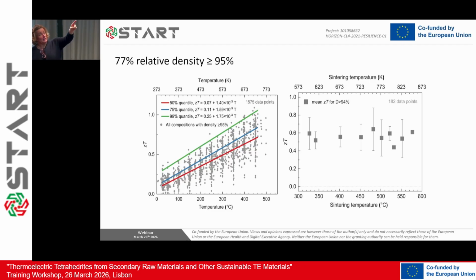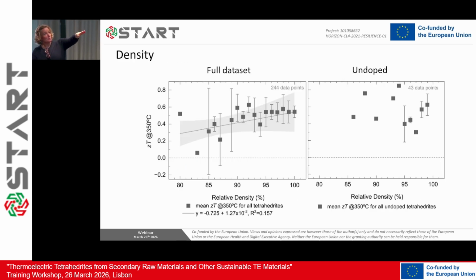Another thing we did was remove all the data below 95, because that data is very scattered and very bad. Remember also that density enters explicitly in the calculation of thermal conductivity. So if you use a very low density, you're going to have a very low thermal conductivity, and it might be wrong. It can be artificial, and I think that's one of the reasons why we have this dispersion.